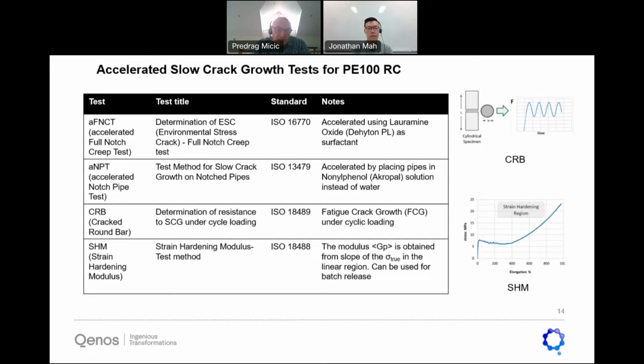So the 2 tests, the accelerated FNCT test and the accelerated notch pipe test, are actually accelerated versions of the existing testing standards. We already had these test methodologies, but we needed accelerants, and what we see here is that they are accelerated with the use of surfactants. The accelerated FNCT test is carried out on compression molded plate specimens, so there is no influence of residual stress imparted on the material during processing. That has an effect on the results. The accelerated notch pipe test, on the other hand, is done on a finished article, which is pipe, which has all these processing influences on the pipe.